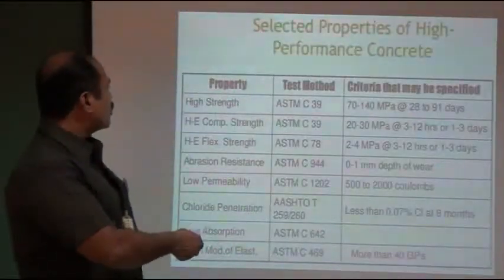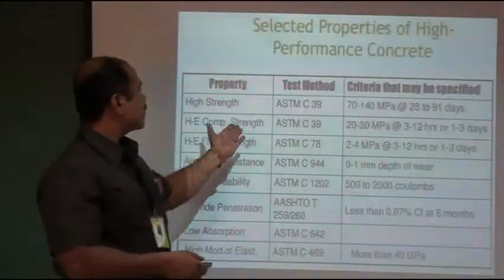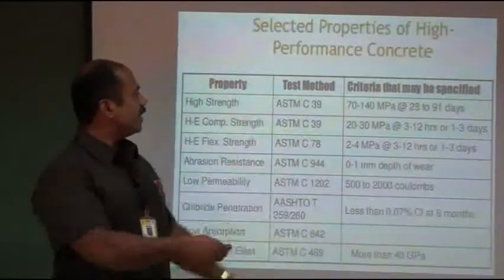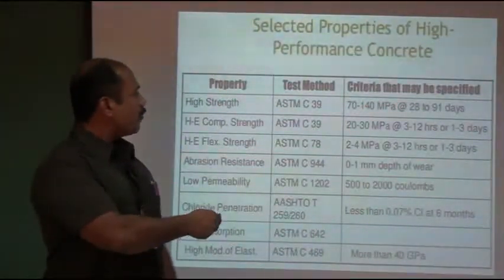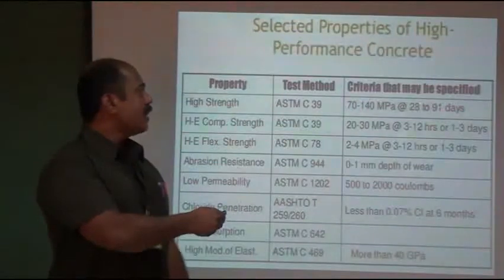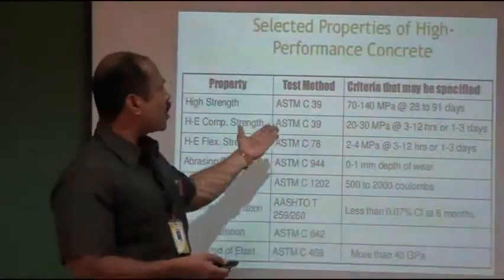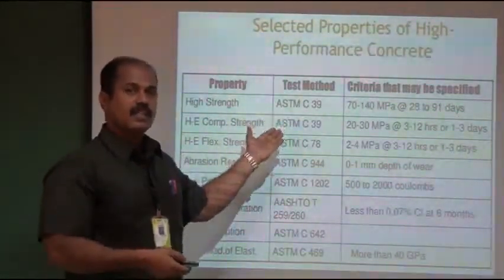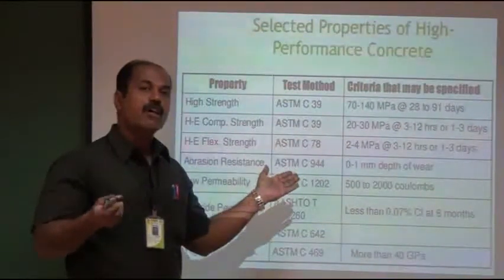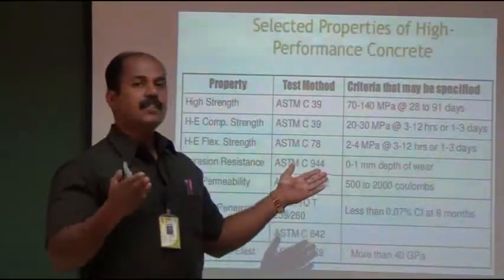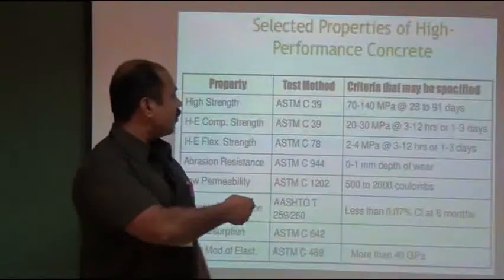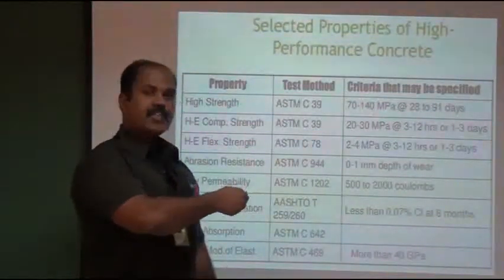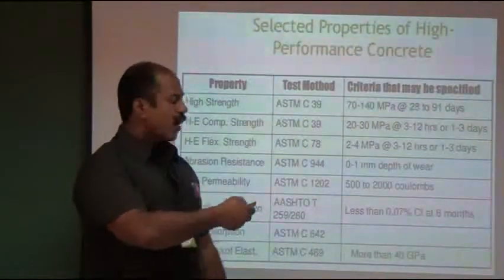So what is the strength behavior of high performance concrete? It reaches 70 to 140 MPa at 28 days to 91 days. In conventional concrete, it is not possible to reach this much strength. Conventional concrete may reach 70 at maximum, but high performance concrete reaches up to 140. That is the main difference between conventional and high performance concretes.